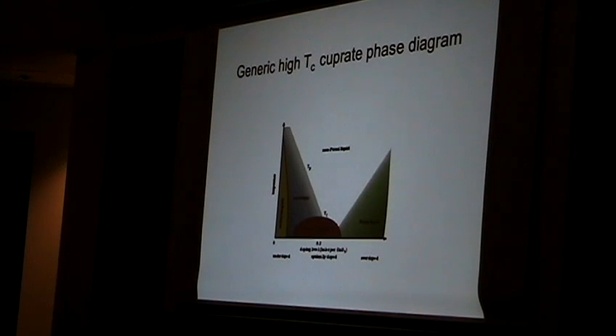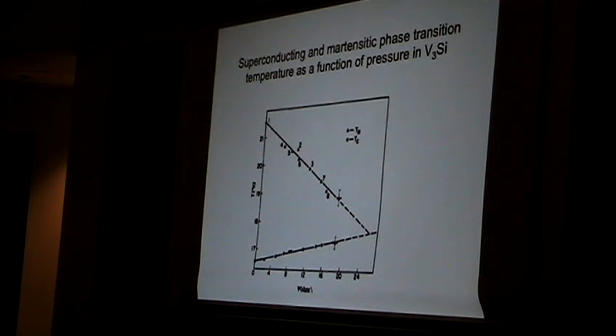This is true, for example, in the generic cuprate phase diagram. As far as I know, the pseudogap phase does not survive below this DC line. I'll give one other example here from the old days of the martensitic transformation and what were considered high TC materials in the old days, A15 superconductors. This line here is the superconducting transition temperature of vanadium-3 silicon.